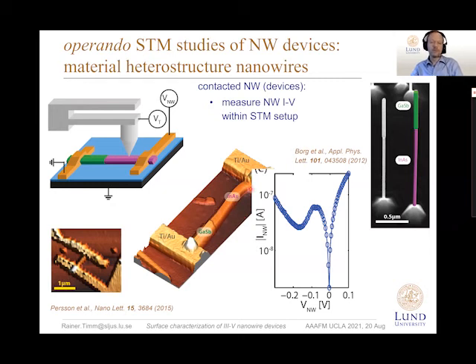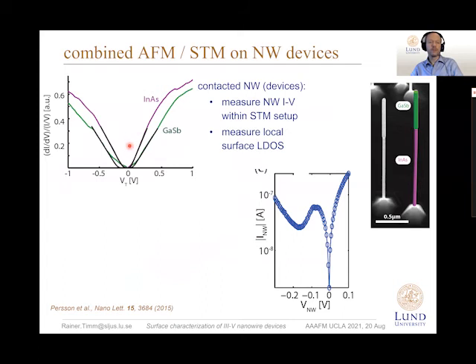Once we find the nanowire, we switch to STM mode and move the STM tip carefully along the conducting nanowire surface, taking STM spectra step by step along the nanowire. We have spectra on the InAs segment and on the gallium antimonide segment. However, these show no sign of diode behavior or Esaki behavior, as we see from the transport data — yet it's the same nanowire, the same structure studied simultaneously. This shows that the surface can behave very differently than the inside of the same nanowire, in this case due to a quaternary, very thin surface layer all over the structure.